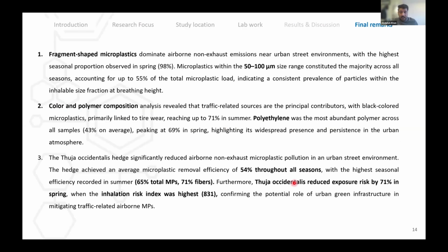In conclusion, I can say that fragment-shaped microplastic was the most dominant, with the 50 to 100 micrometer size range, and color composition and polymer composition revealed that polyethylene was the most abundant polymer across all samples, peaking at 69% in springtime, highlighting its widespread presence and persistence in the urban atmosphere. And finally, Thuja occidentalis has significantly reduced airborne non-exhaust microplastic pollution in urban streets.